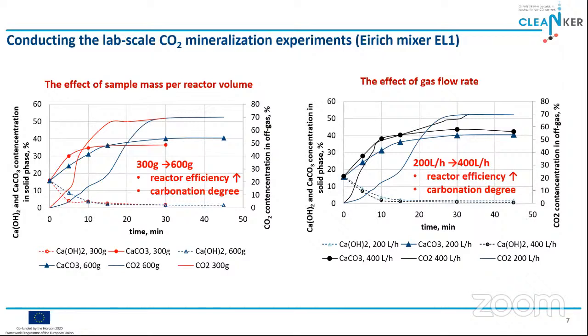As for the changing parameters, such as flow rates of both gas concentration and the mass of the samples, they indicated that they can accelerate the CO2 mineralization process due to improved contact of the phases, up to a point. As you can see here, while the mass increased, the reactor efficiency and the carbonation degree increased up to a point, as well as when the gas flow increased. These are again in the first phase, in the 1 liter intensive mixer.